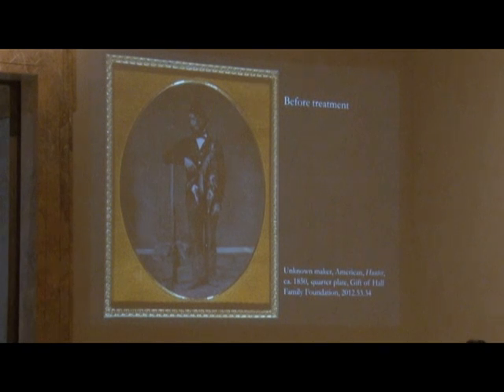Another frequent problem is related to the cover glass. This plate, as you notice right away, has all these white spots scattered over the image. This is accumulated dust and glass corrosion material. And since the daguerreotype is a mirror, you're seeing a reflection of all these spots. So this is doubly spotty looking. And at this point, the three-dimensional illusion of the daguerreotype is hindered, and it's really obscuring the image. The plates are supposed to be sealed in an image package to keep clean, so you might be wondering how it can get so dusty.